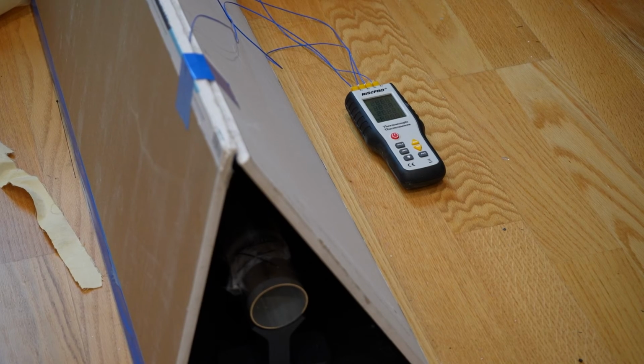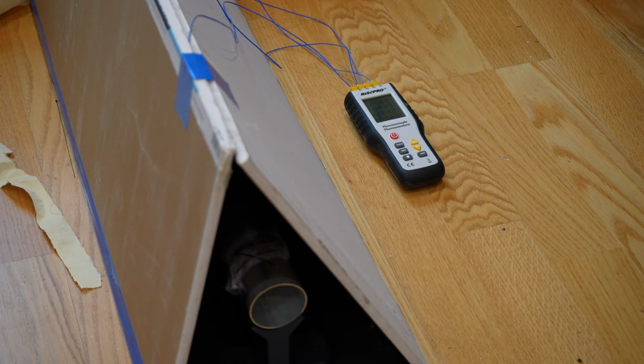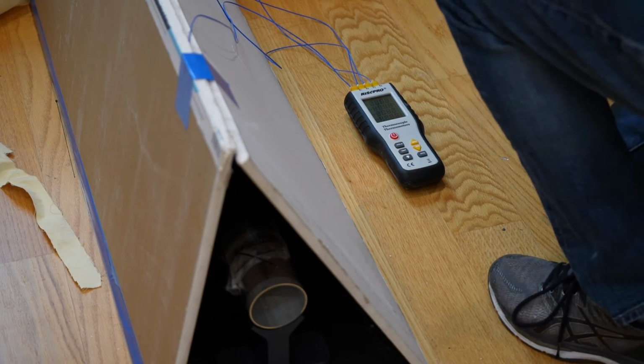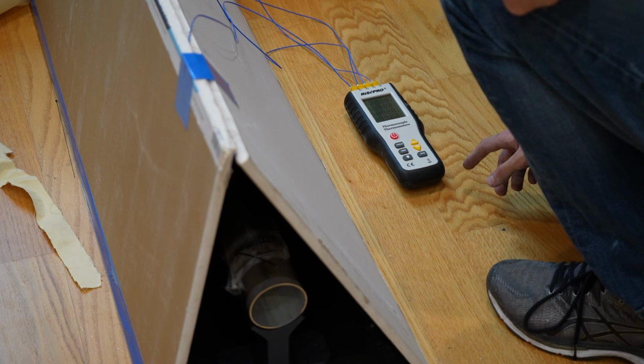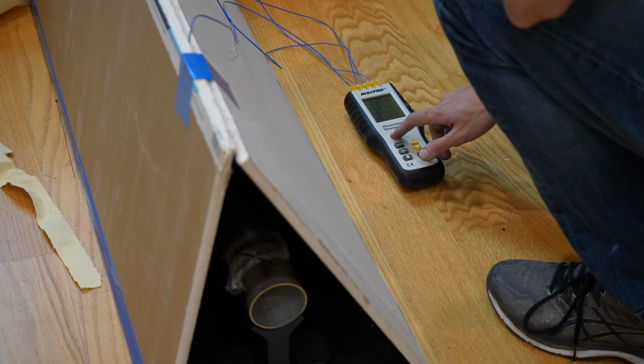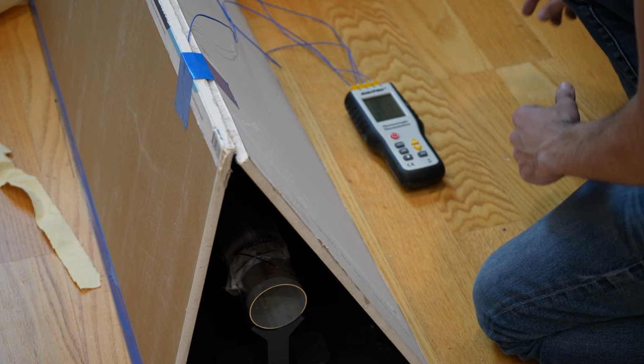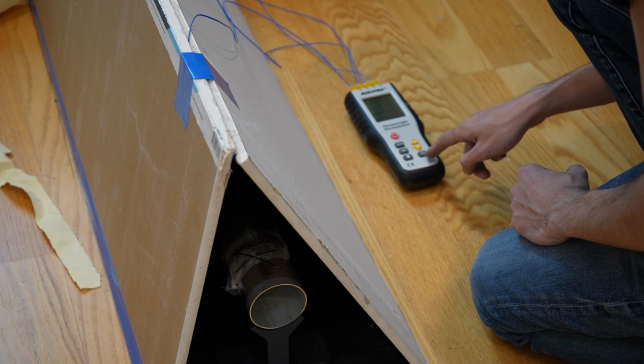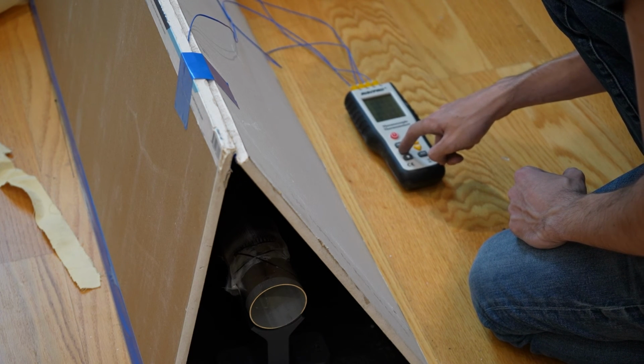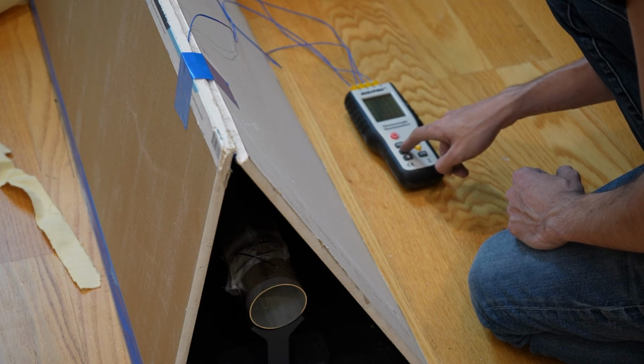I have 4 thermistors in this oven that allow me to monitor the temperature in different portions of the oven, and I use a hot air gun to control the temperature. The tube needs to go through a 9-hour cure cycle, so it takes most of the day, and I try and do multiple tubes at once to make the process a little more efficient. It's really important when you're doing the cure cycle not to heat the tube up or cool it down too quickly, as that can damage the epoxy and reduce the strength of the layup.